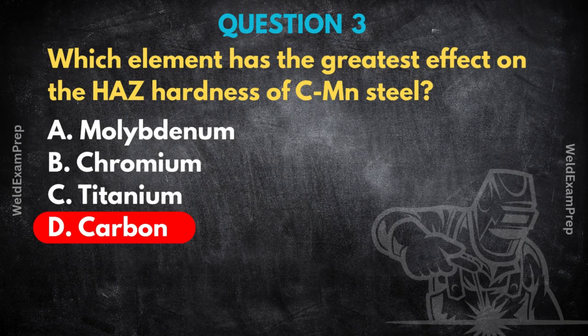Now, if you have a higher carbon content in that steel, it significantly promotes the formation of very hard and unfortunately often brittle microstructures. The main one we worry about is martensite. Martensite, heard of that? Yeah, it's a super hard, often needle-like structure. Higher carbon means more potential to form martensite, especially if the cooling is fast. And hard means brittle. Hard often means lower toughness, yes, more brittle.